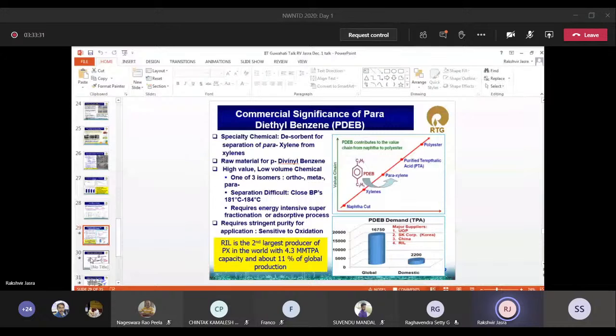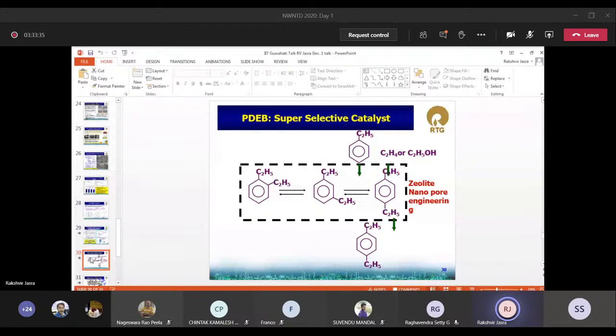So what we did, now the pores of our zeolite, zeolites are nanopores. The zeolite which we use has an elliptical pore opening of 5.6 by 5.2 angstrom. Now the opening of this zeolite pore was done in such a way that only paradiethyl benzene can come out, while ethyl benzene can get into the pores. All other isomers or any other similar compound cannot get into the pore. Like here I have shown, here we put ethylene and ethyl benzene. Ethyl benzene and ethylene will go into the pore. You will get all these three isomers. But what will come out as a product is only paradiethyl benzene, because the others, because of their non-symmetry, cannot come out of the pore. We had changed the pore opening in such a way.